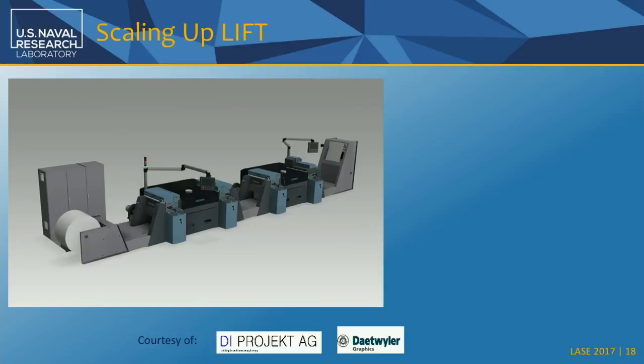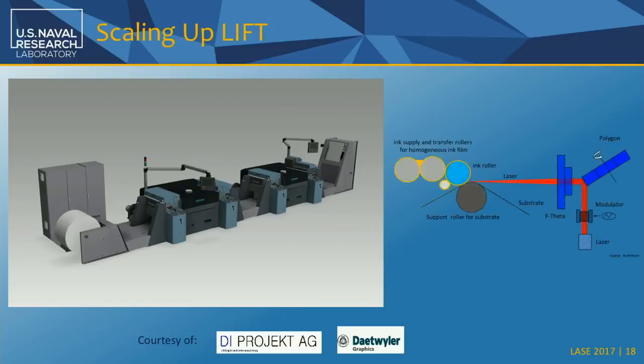One of the comments that is always made about these techniques is that they're serial in nature, and how fast can you actually print? And I want to thank Dr. Hennig here for letting me use this slide from a project that he worked on years back, where they designed a large throughput roll-to-roll printer process based on laser forward transfer. Instead of using laser forward, they use laser back transfer, but it's still a transfer mediated process using lasers. In this case, you had a continuous roll with the ink that will be coated. The ink will be semi-transparent to the laser, which heats up the metal backing, and that will create the bubble, and that will lead to the droplet being ejected.